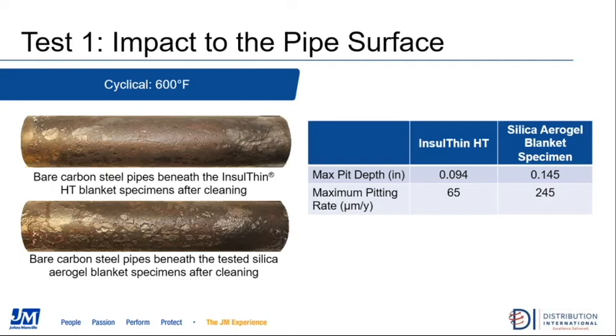So we look at the results of test 1. What you're seeing there on the left-hand side of your screen are pictures of the actual pipes from the test. So when the laboratory was done with this test, they took the pipes out of those vats, they cleaned the pipes, and then they analyzed it and provided the results. The top pipe that you're seeing there is the Insulthin HT sample. The bottom pipe is going to be the Silica aerogel sample. What we're seeing on the table to the right there is going to be the maximum pitting depth in inches. And then what we're looking at here is how far those pits extended into the metal. So we reviewed from before when we talked about pits, that is that highly localized form of corrosion that extends into your pipes. And what we can see on the Insulthin HT sample is that it was dramatically less than the Silica aerogel sample.